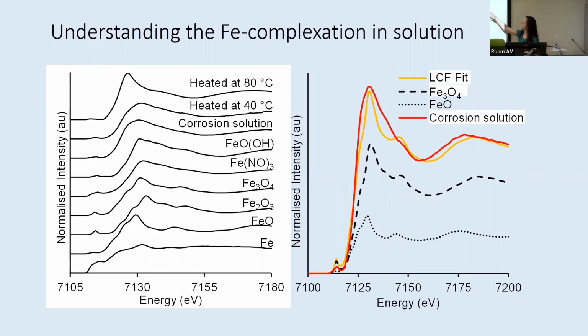What you can immediately see is we've got our frozen solution, and then we've heated it to 40 and 80, and I'll get into that in just a second. But what's really interesting that you can see is that, first and foremost, it doesn't match particularly well. We've used a range of different fitting methods to understand our data. I've demonstrated one here.